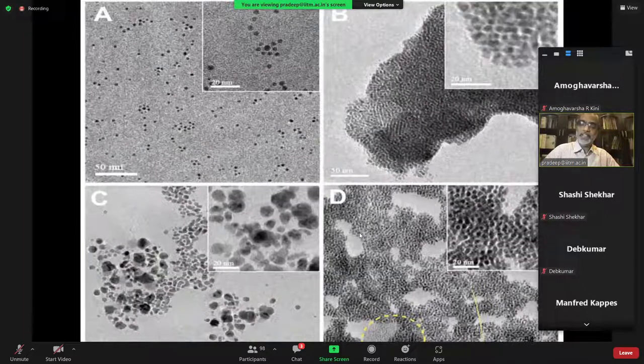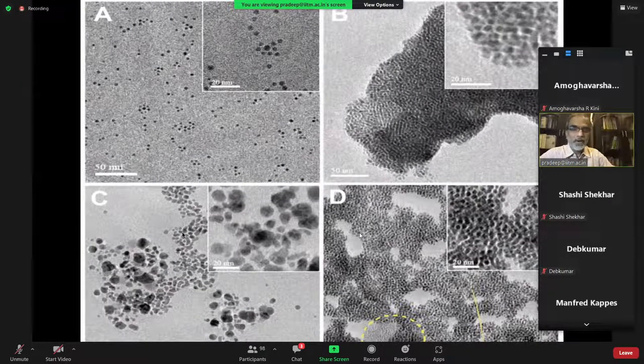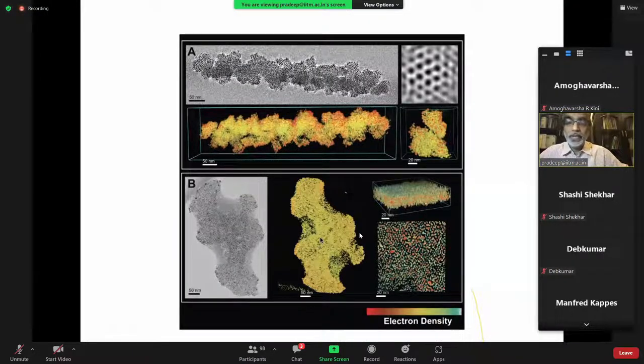monodispersed nanoparticles, and several polydispersed particles of one diameter or another diameter can be taken. And you can prove that even if it is highly polydispersed, you can create monodispersed particles. And these superlattice crystals, as I told you, are not very big, but you can image them to find that there is a translational periodicity in these assemblies that you have.